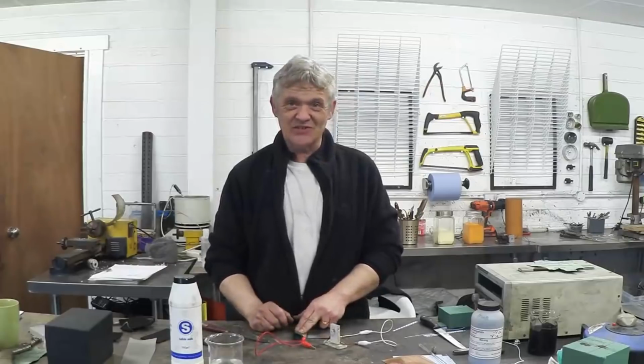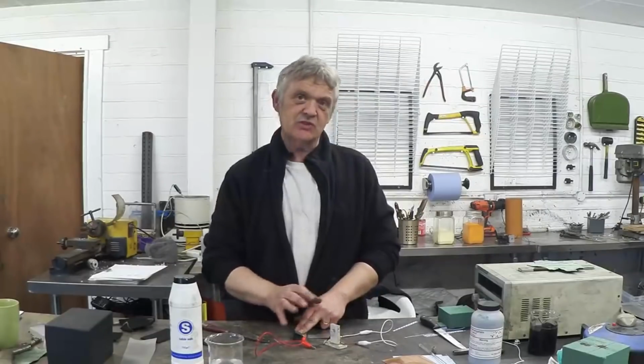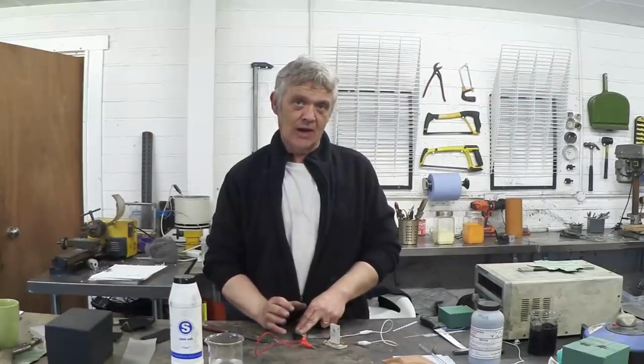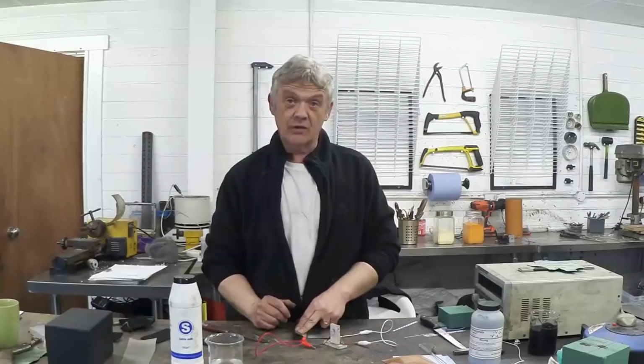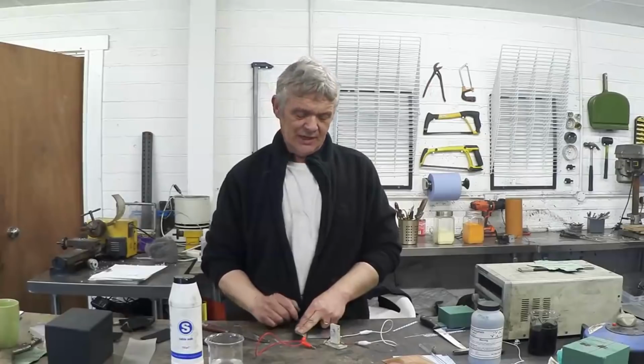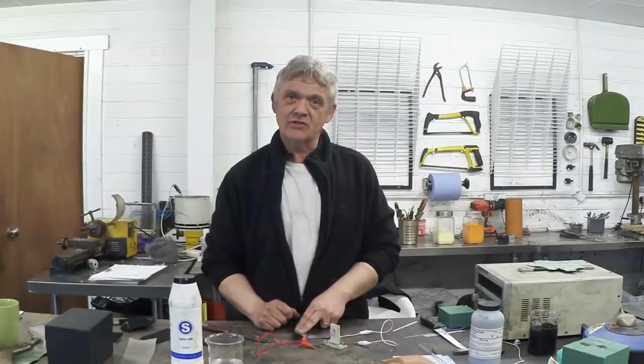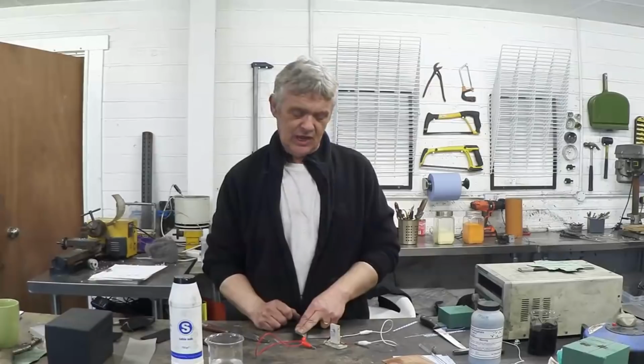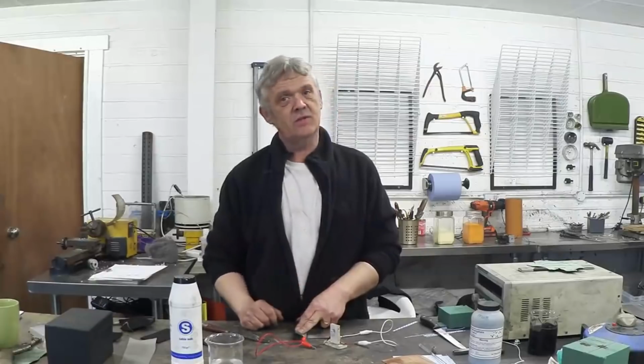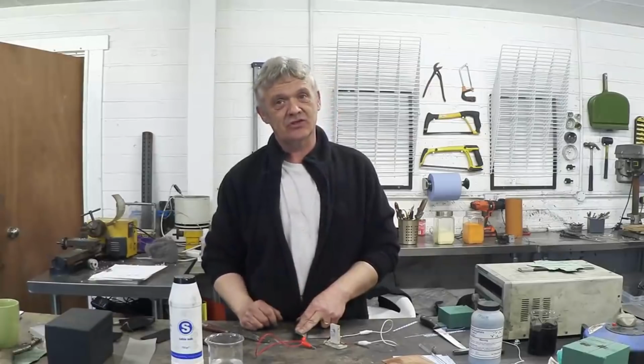And it gives awesome results. This will last until the magnesium is eaten away. It's about 1.85 volts that you get from it. It'll last for as long as the magnesium lasts. When you need to charge it again, then you put more magnesium in there because you are using a catalyst.